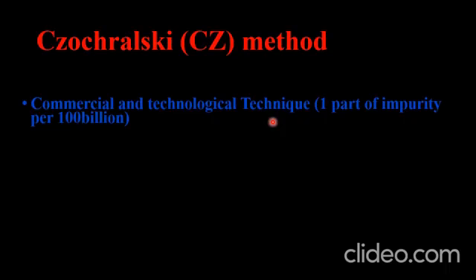The level of impurity using the Czochralski method is in the range of 1 part per 100 billion. That means that if we produce a crystal structure 100 billion times, only one time in 100 billion there could be an impurity. This means that the Czochralski technique produces highly pure single crystal material, and that is the reason this technique is widely used to grow single crystals in commercial and technological ways.